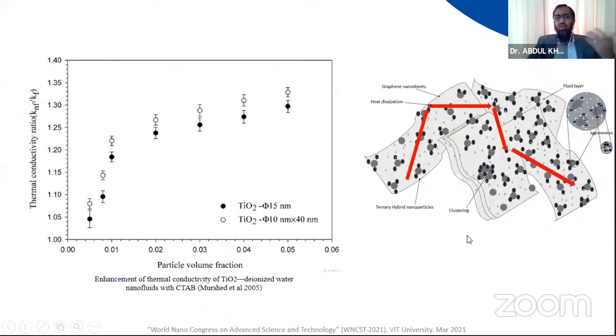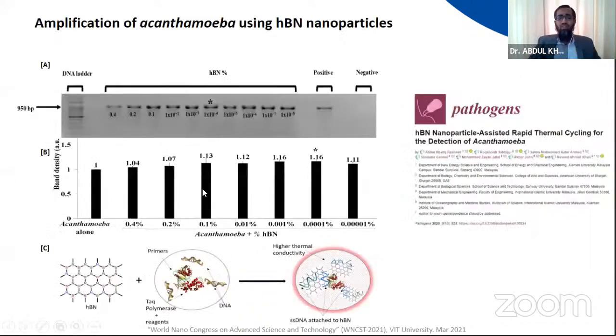So this has been already established by many people around the world, and we use a similar mechanism to justify why we believe the enhanced conductivity effect of nanoparticles will be more prominent in the case of PCR as well. Then we used, for example, acanthamoeba. This was quite a recent study in 2019, if I'm not mistaken. We used hexagonal boron nitride, which is again a 2D material. We used a similar material because it comes from a different family of materials. Nevertheless, we wanted to establish if this can help as well.